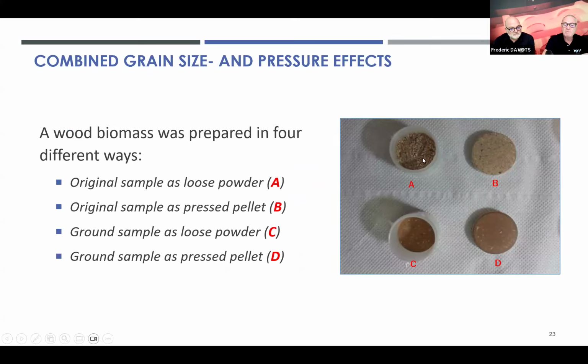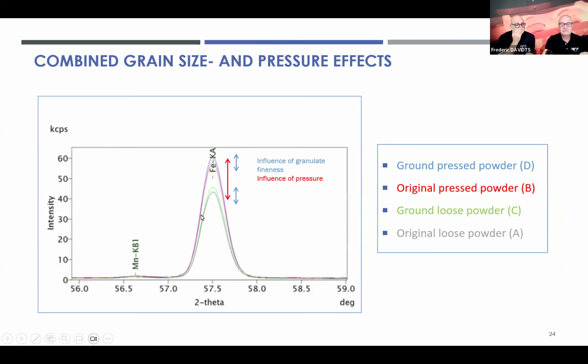So this was a biomass prepared in 4 different ways. So it's each time the same biomass, so each time the same concentration. And sample A here is the original sample, measured as a loose powder, and then the original sample was pressed as a tablet. Then this biomass was ground by a swinging disc mill, and then that sample was also pressed. So what we can see here for iron, for example, if we look at the original loose powder, we have here an intensity of, let's say, 40 kcps.